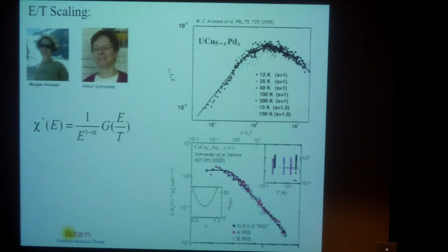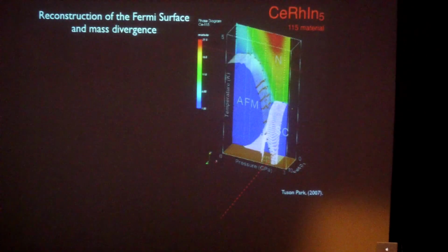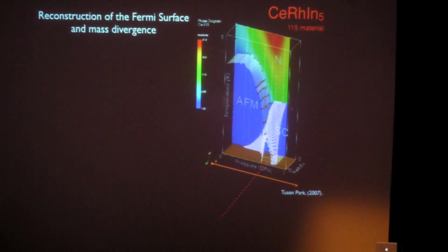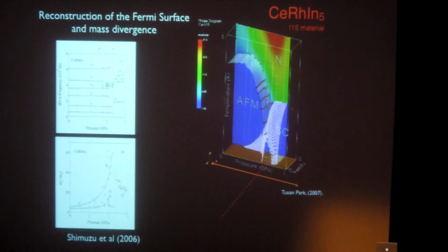Here's another sign of unusual behavior, the E over T scaling in the magnetic fluctuations measured in these two different systems by Meigan Aronson and Almut Schroeder, tells us that temperature is the only scale. This is what we would interpret as physics below the upper critical dimension, and yet the standard model has us above the upper critical dimension in 3 dimensions. Here is some more data showing how, as you go through this phase transition in cerium rhodium indium-5, the Fermi surface jumps in its volume.